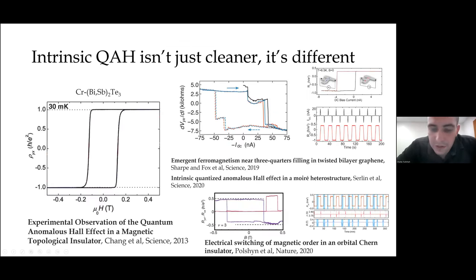So the first indication that this was the case was that we found that in every intrinsic Chern insulator we studied, so on the top is shown twisted bilayer, the bottom is twisted monolayer bilayer, which is a related system, also graphene, there is extremely strong coupling between transport currents and indeed transport properties and current and gate excursions. So chemical potential and charge flow through the device both couple extremely strongly to magnetism in the sense that they can flip it.